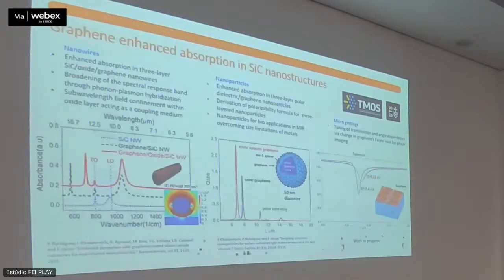And we have started demonstrating this in quite a few areas. So the nanowires that I showed you before, for example, I'll explain here. If you had only silicon carbide nanowires, you would have a response in this area, don't worry about that. But this would be the surface phonon response in the field, which is really the reststrahlen band. Once you've coated the wire with graphene, you actually start having a split double response, and you extend it beyond the reststrahlen band. And then you can start tuning it by applying, for example, a gate, which is extremely interesting. You can play the same games with nanoparticles. And the very interesting part is that if you wanted to use these nanoparticles for biological environment sorts of applications, this will be really useful because, for example, they can absorb a lot of heat.